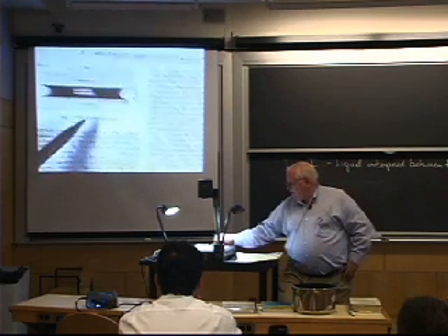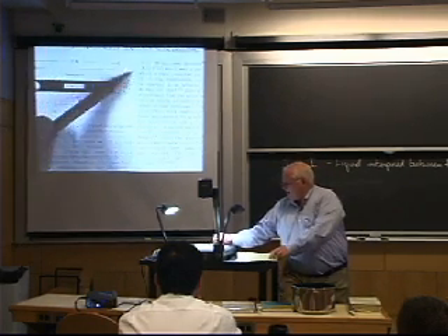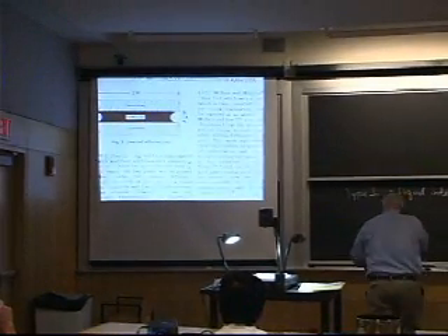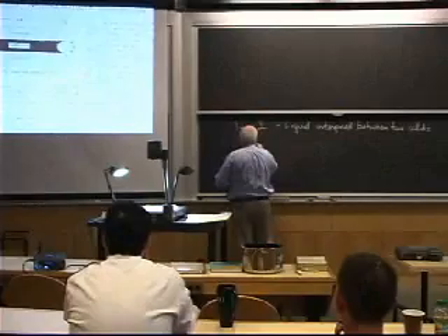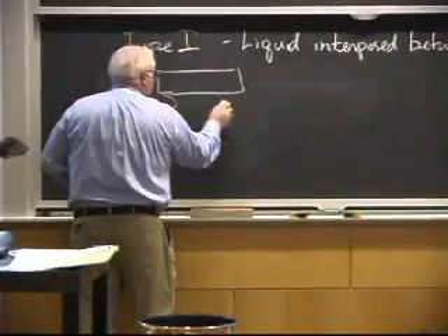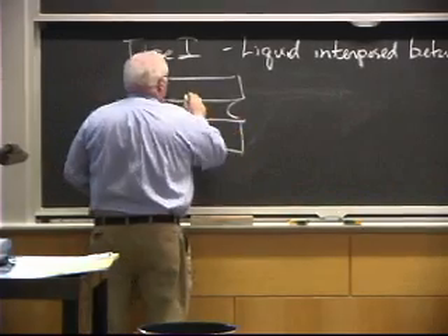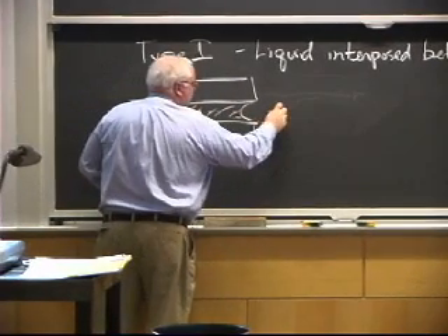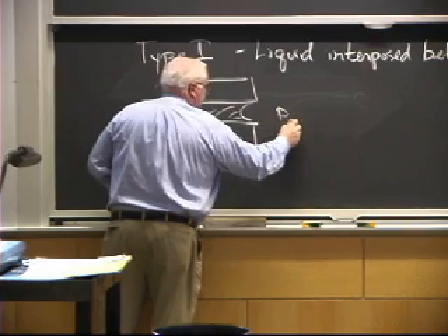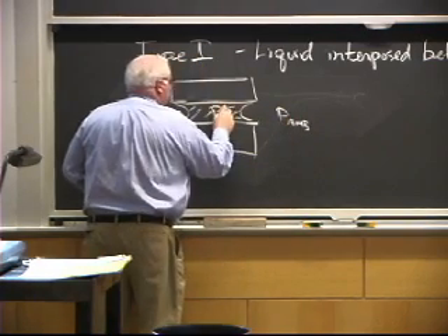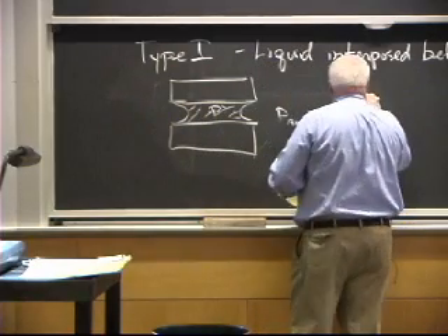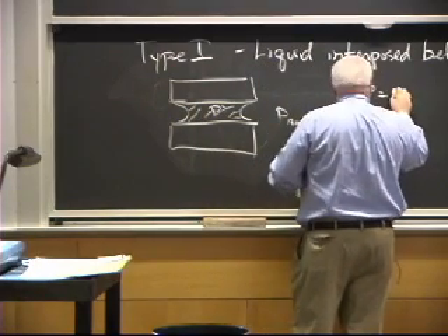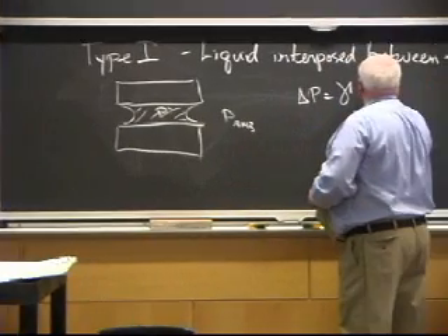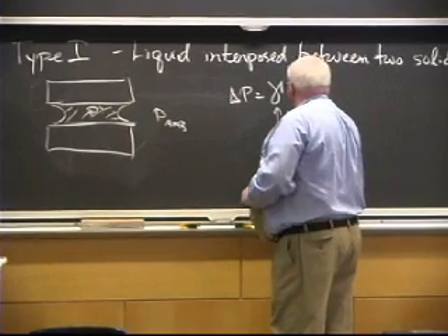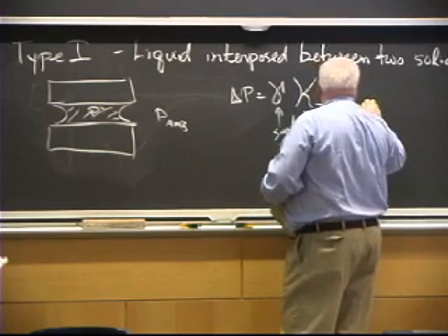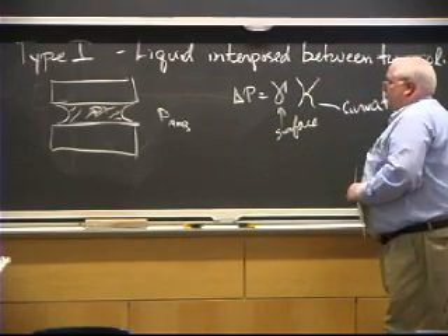And the way it does it is basically, if I have a thickness D and I have a diameter, if these are two discs, simple discs, 2R, then it turns out there's a pressure differential. Let me redraw this quickly. There's a pressure differential between out here, which is the ambient pressure, and the pressure in here. And the difference in pressure is given by the surface tension times the curvature, which often is kappa. So that's surface tension, and kappa is the curvature of the surface of the liquid.